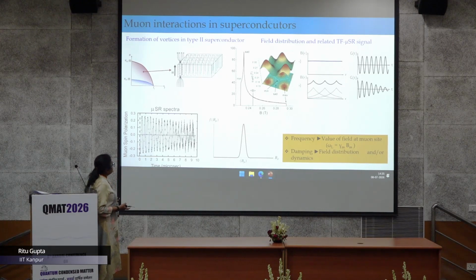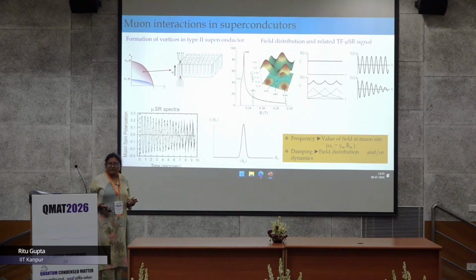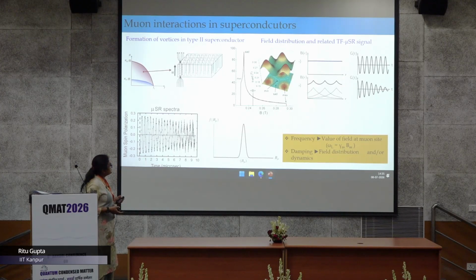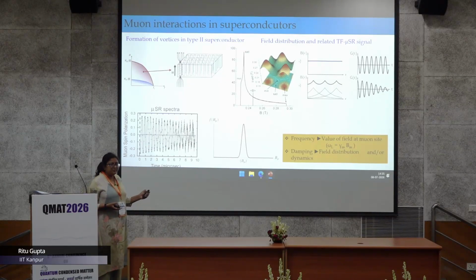So the muons bombarded into the superconductor in the vortex state will see three different fields. Some muons can stop inside the vortices, some muons can sit between two vortices, and some muons can sit between three vortices. So they experience three different fields. When the muon sits between three vortices you have a cutoff, and for muons sitting between two vortices you have a saddle point and then a tail at the higher field. So this asymmetric line shape you should see if you have a well defined vortex